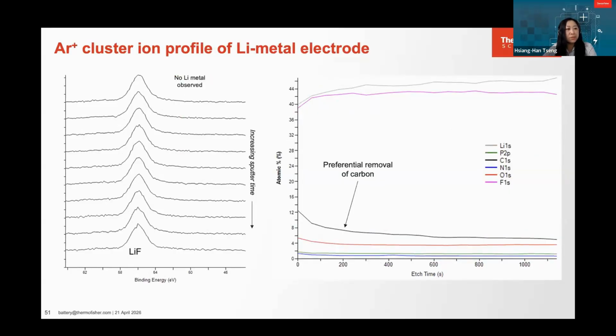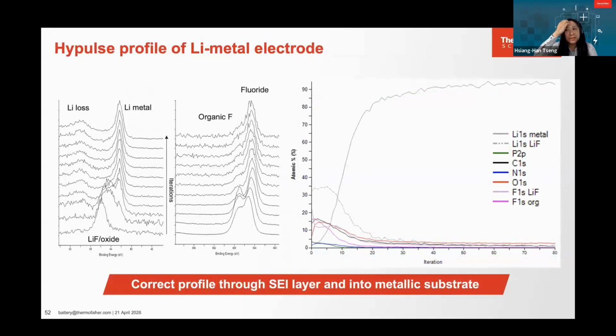So we then try to do cluster ions because that should give us a slightly gentler effect. And it is very gentle. If you focus on the lithium spectrum, you will see that it looks like we're always hitting the same surface, despite that no chemical damage can be observed. What we would like to see is some contribution from the underlying metallic lithium, and we don't see anything. So this probably means the etch rate is not sufficient to go through the SEI layer. But in the next slide, you will see our latest development.